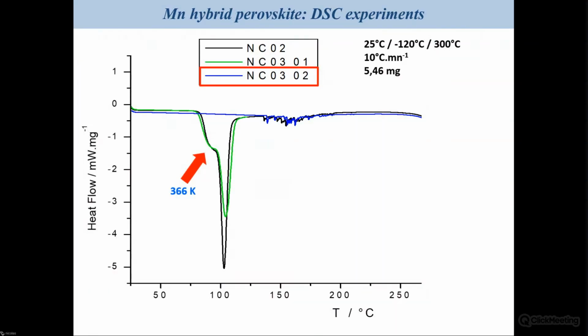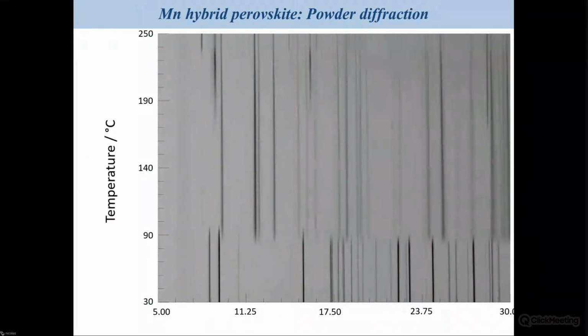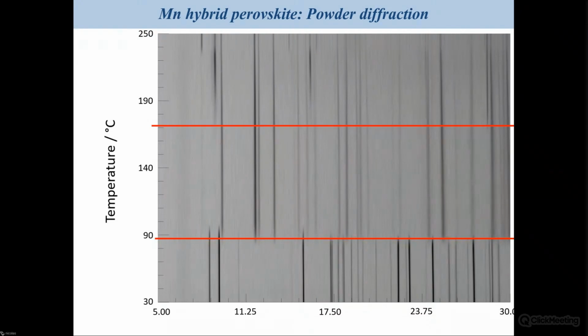And it happens at 366K with some events at higher temperature. So we realized the powder diffraction experiments on that temperature range. And this is the result of the summation of the different powder diffraction experiments. You see that a very huge transition appears close to 100 Celsius degrees, and you have smaller events at higher temperature.